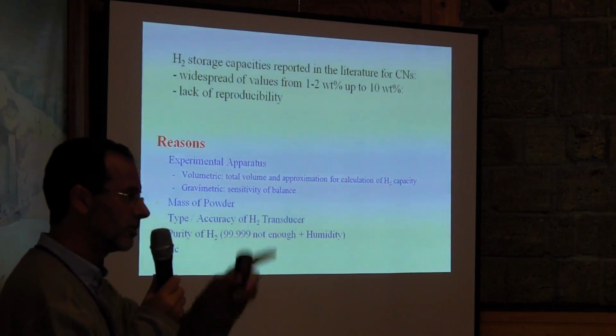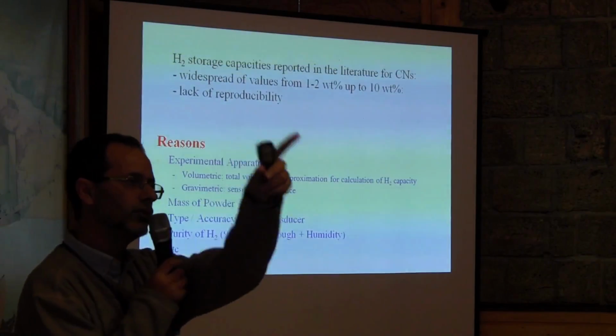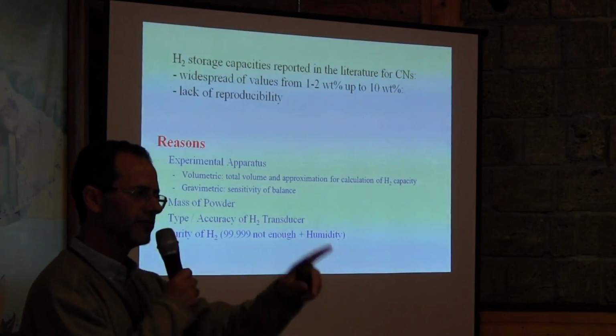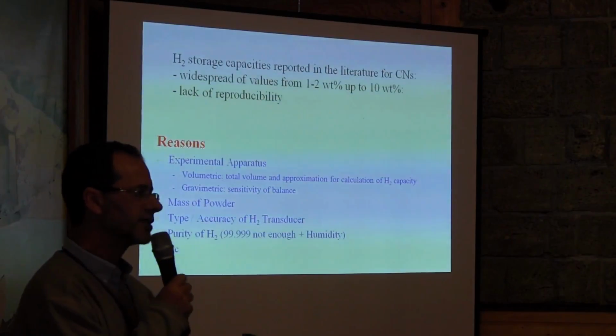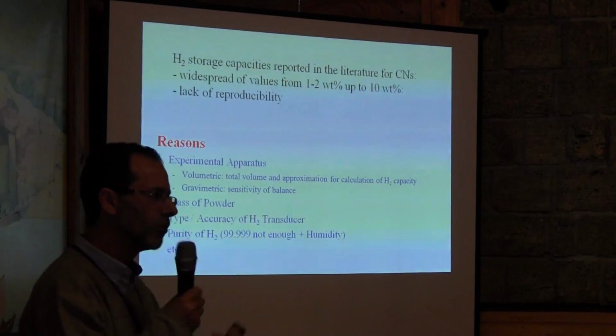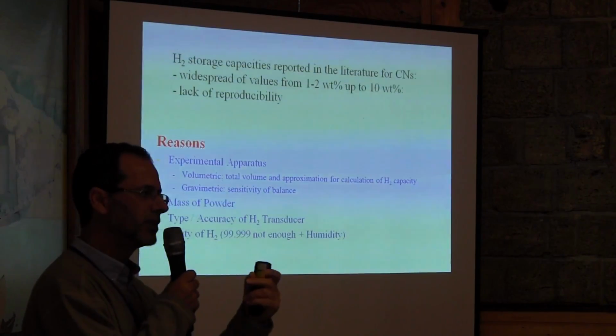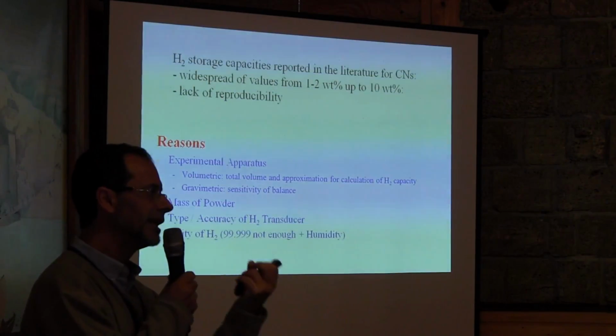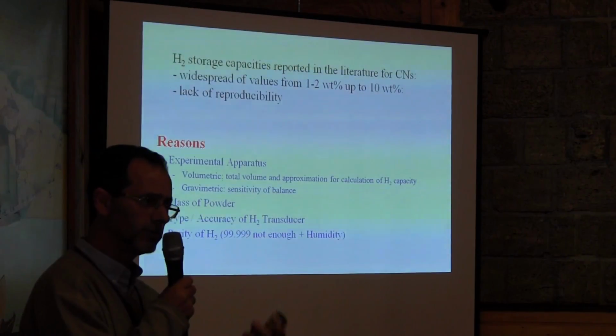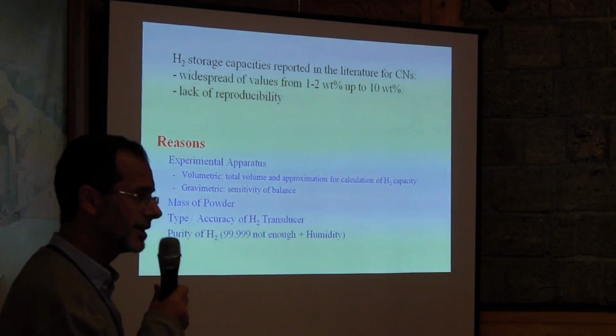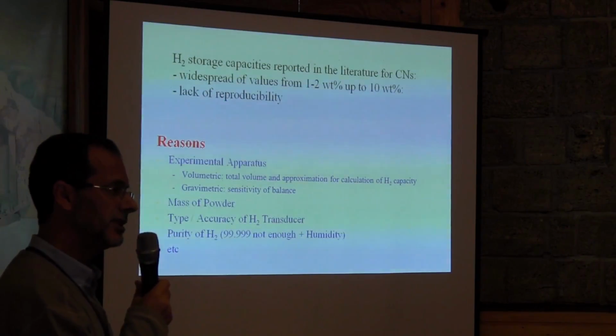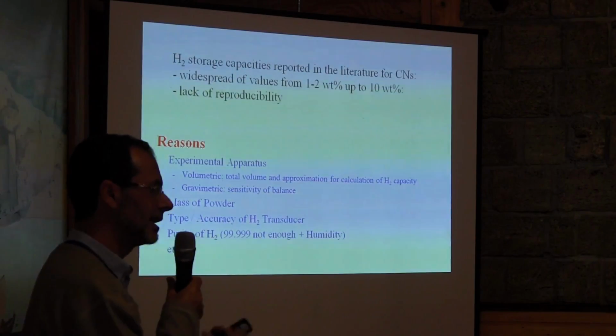And I did my test. So I make a U-tube like this, and I flow, and I have a tank of liquid nitrogen. So when I flow, I can hear bubbling. What is bubbling? That means the hydrogen, when it flows through the liquid nitrogen, traps all the humidity. So people who work with hydrogen or other gases, to avoid this kind of humidity, because it interacts with your samples, you need to use this kind of technique.